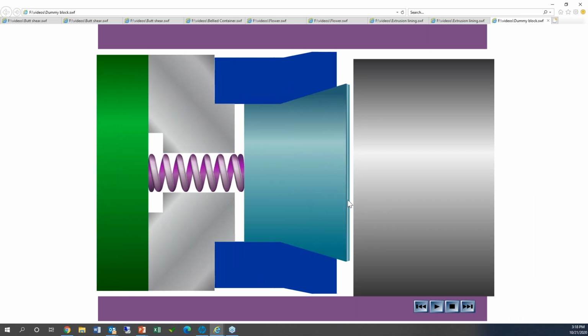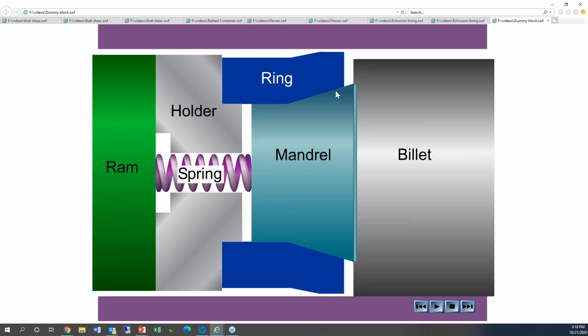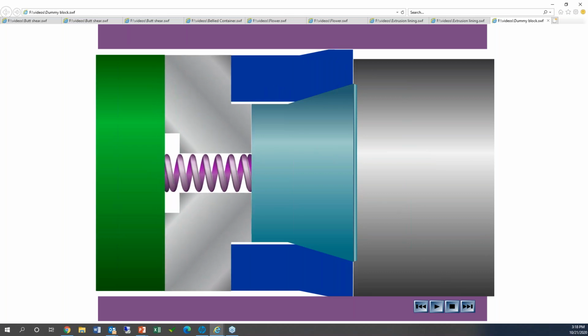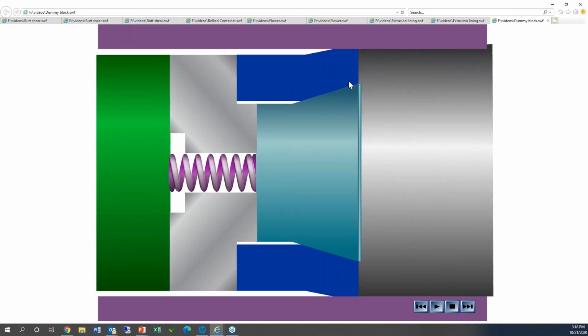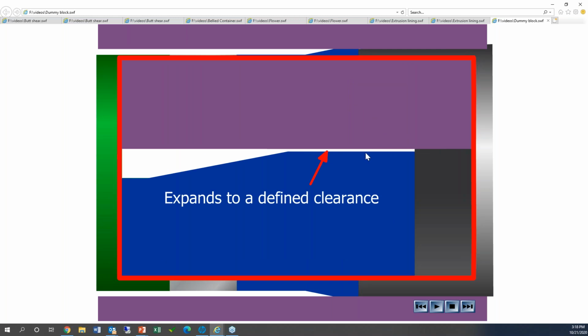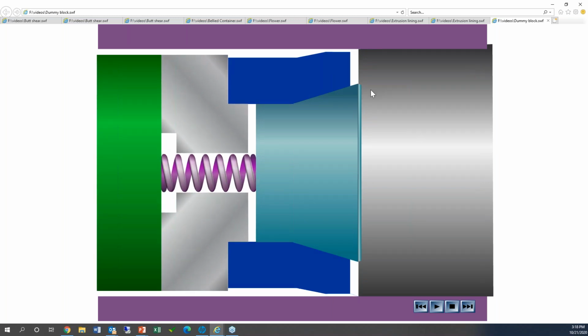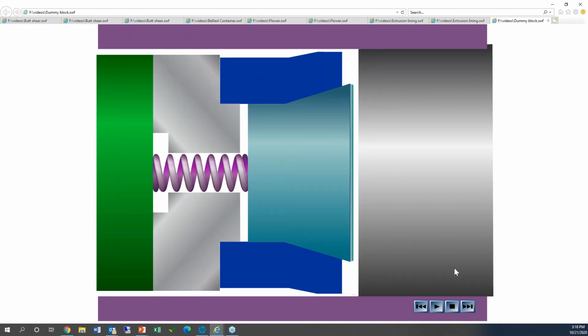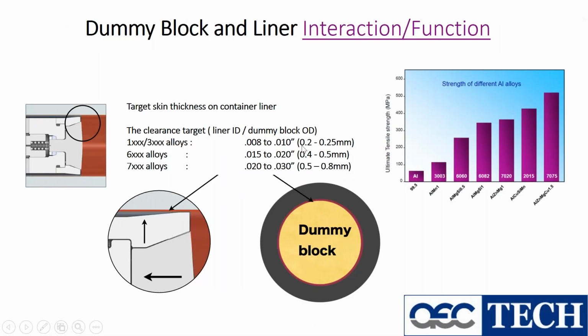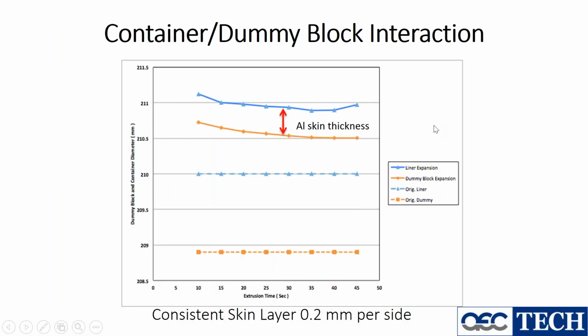When we look at that function again, because I just like to show a video, again, it's very important that as the block expands, it gets into this area and then leaves that small gap between the OD of the block and the ID of the container. Maintaining this gap throughout the cycle and at the end of the cycle as it pulls back is extremely, extremely important. Why? Let's get into the why. That aluminum skin thickness that's inside there, under temperature and pressure, as the liner starts to expand, which it does,